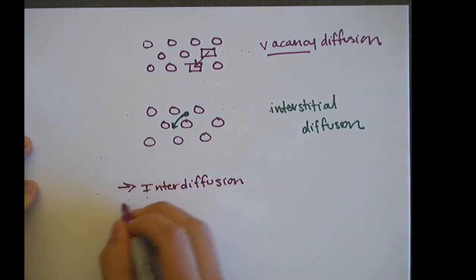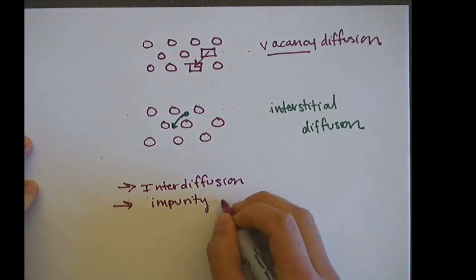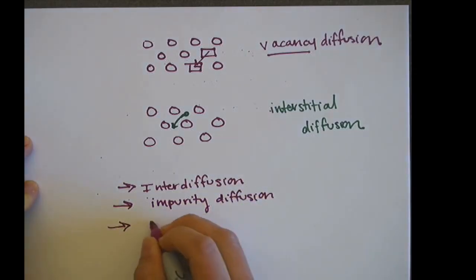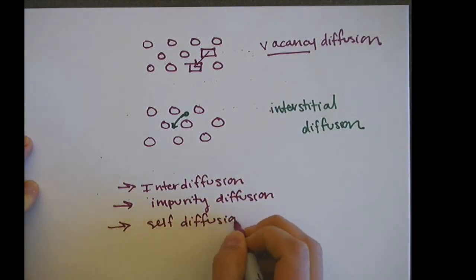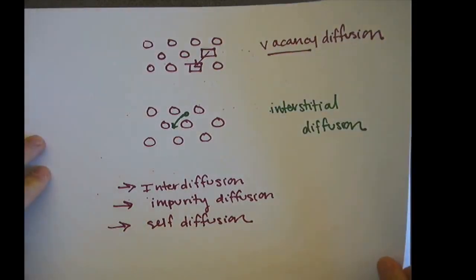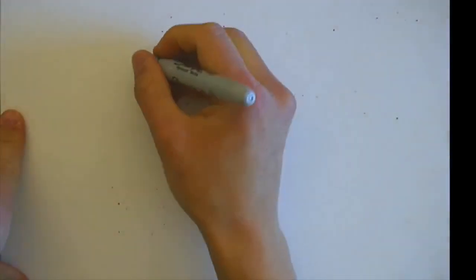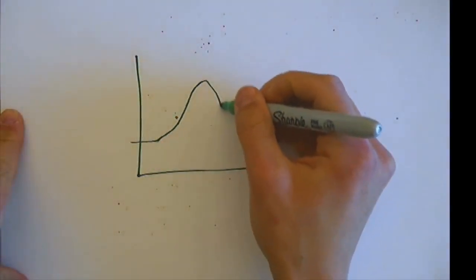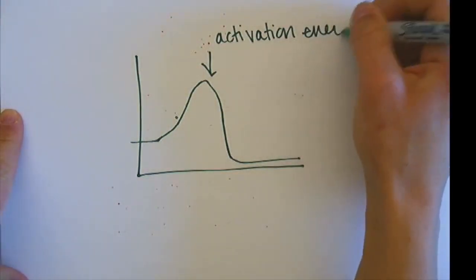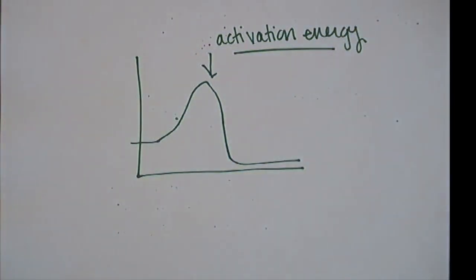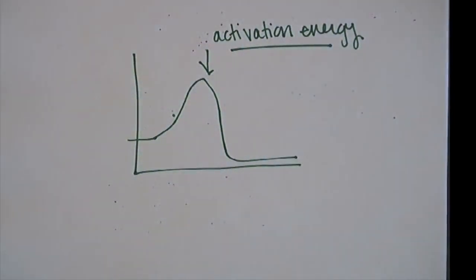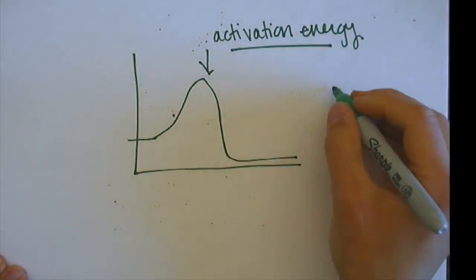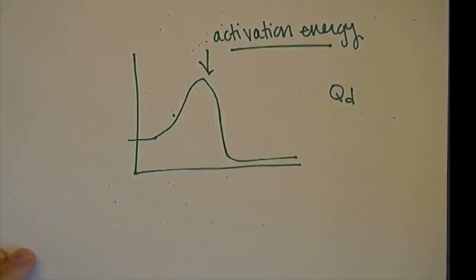So the process whereby atoms of one metal diffuse into another is called interdiffusion, also termed impurity diffusion. The next one that we talked about was self-diffusion, and self-diffusion is where atoms are all of one type and they exchange positions inside. So I mentioned activation energy. Here we're going to draw a graph of the activation energy, and I put a little bump here for a reason. That's the amount of energy required to strain the lattice so that we can actually have those atoms moving from vacancy to vacancy or from interstitial to interstitial. That bump will be a lot smaller for the interstitial diffusion, a lot bigger for the vacancy diffusion. We will denote that QD in the equations to come.